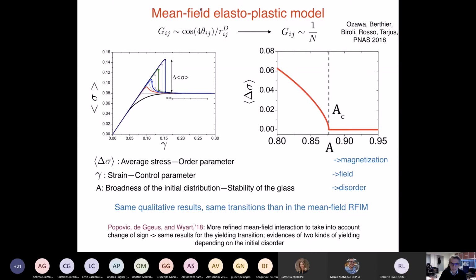This is good in the sense that we really find the same features that I discussed before for the random field Ising model. Depending on the value of the disorder, we have 2 different ways in which the system responds. If the disorder is strong, the system responds in a smooth way. And if the disorder is small, the system responds through a real phase transition, which is discontinuous. And one can really do almost a mapping between the 2 systems, meaning that what is the magnetization in the random field Ising model would be the average stress, the order parameter. What would be the external field in the random field Ising model would be the strain, the control parameter, the one that we change. And then what would be the disorder is the broadness of the initial distribution.